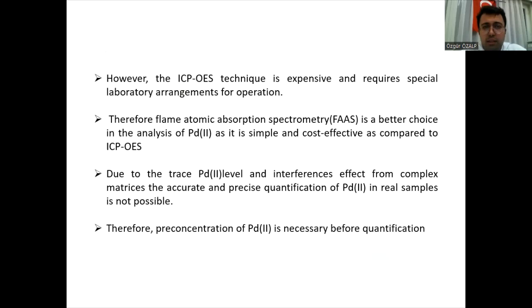However, this ICP optical emission spectroscopy technique, I say again, is expensive and requires laboratory arrangement for operation. And then another instrument, flame atomic absorption spectroscopy, is chosen in the analysis of palladium. It is simple and cost effective compared to ICP optical emission spectroscopy. But due to the trace palladium level and interference effects from complex matrix, quantification of palladium in real samples is not possible. Therefore, preconcentration of palladium is necessary for quantification because the preconcentration factor is very important.